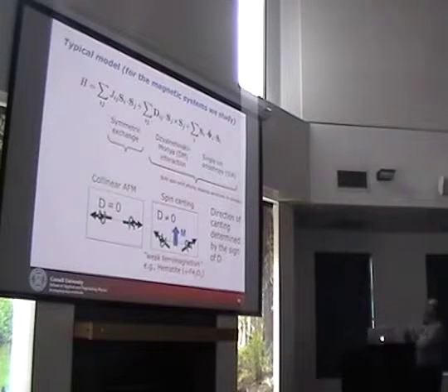What is that? Well, just in case this is completely foreign to you, symmetric exchange interactions in oxides are mostly linked to antiferromagnetic spins that look something like this. But when we turn on these relativistic effects, like the Dzyaloshinskii-Moriya interaction and single-ion anisotropy, these lead to a canting of these spins. This is what is referred to as weak ferromagnetism. It's the origin of magnetization in things like rust.